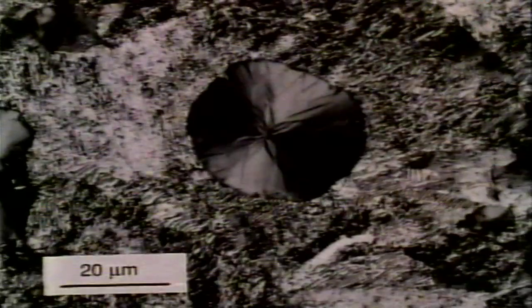However, the mechanical properties of SG iron are good when compared with other cast irons. The addition of magnesium changes the graphite from the flake form found in grey iron to the spheroidal form shown here. Spheroidal graphite is a smaller microstructural stress concentrator than flake graphite, which tends to easily initiate cracks in grey iron. This means that SG iron is much tougher.